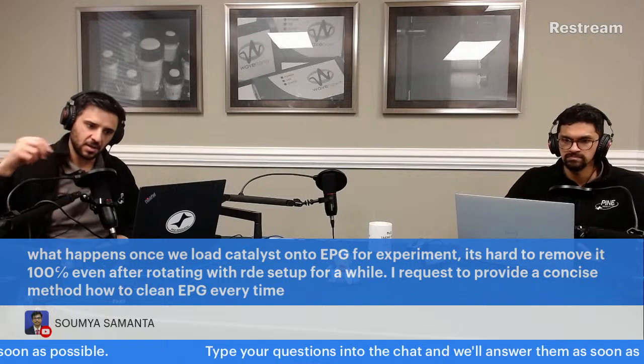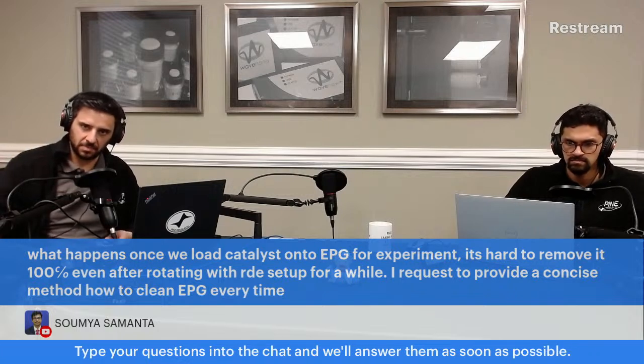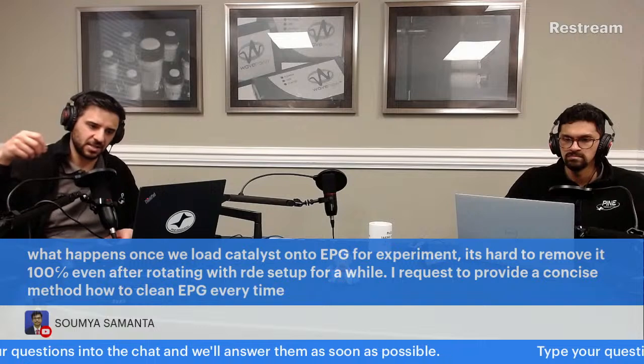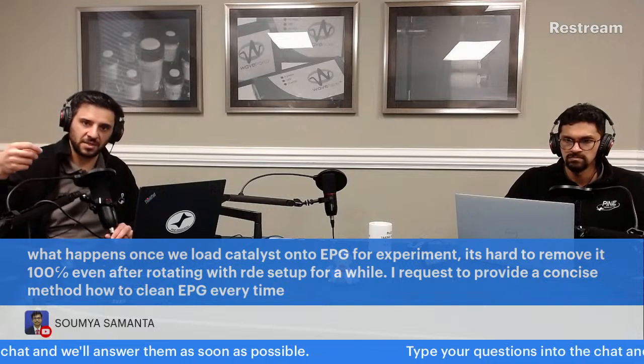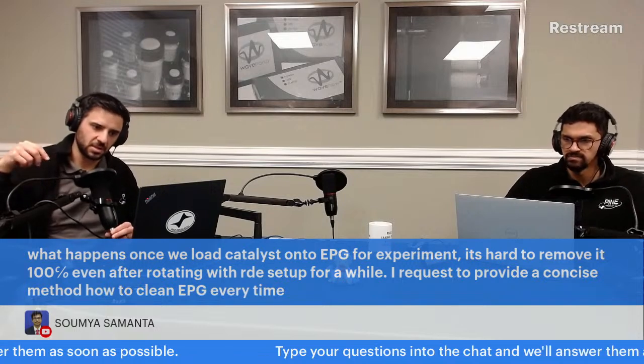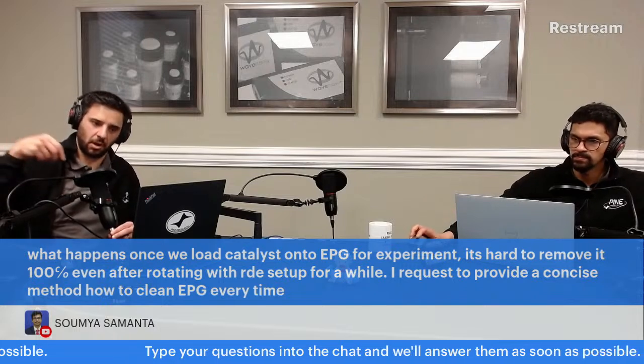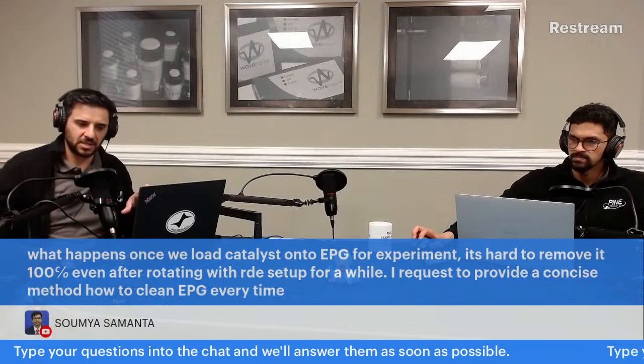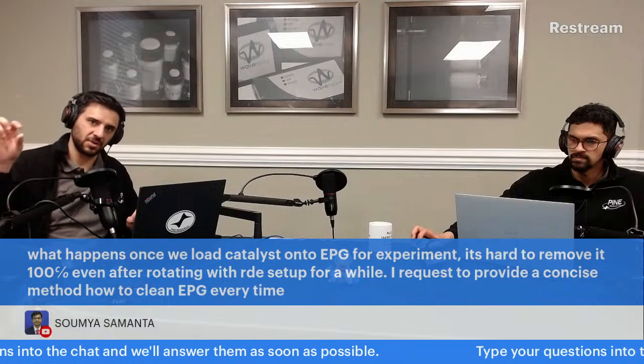that you're still circling around in. Because that's the problem, you might just be depositing it, causing it to embed. You don't want to polish with the stuff that you just removed from the surface. You want to polish, but you have to use that method to scrape it off in the first place. So I hope that's clear. So multiple steps of polishing, rinsing with deionized water.